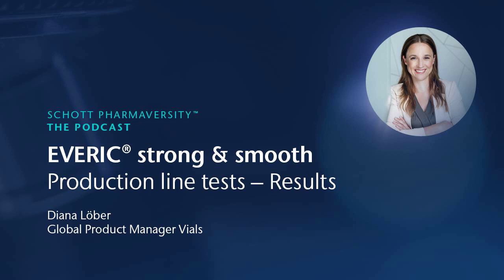And secondly, I think with that trial, we showed that the coating is stable, because this is one worry our customers might have, that the coating is not stable. And what we showed is that there were no particles found related to the coating, neither in the filled medium nor in the washing water. And also washing and depyrogenation didn't have an impact on the performance of the coating. And I think the third point would be that the coating, like already mentioned, majorly helps to decrease the cosmetic reject rate, which can heavily reduce your costs.